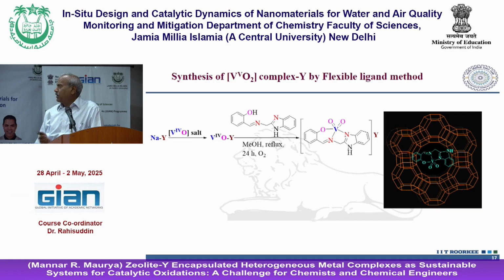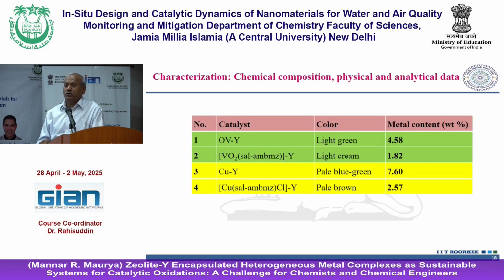Okay, in the IR. Now, how to characterize? That's the question. Characterization, when you have ICP-MS, you can find the metal content. Okay, through FESEM, you can find morphology, and also you can find the metal content. Through TGA, you cannot find metal content here. The reason is because you have alumina, you have silica. Silica is highly stable when heated. This will not further decompose, right? So metal content determination through TGA is not possible here. The only possible way is through ICP-MS, and